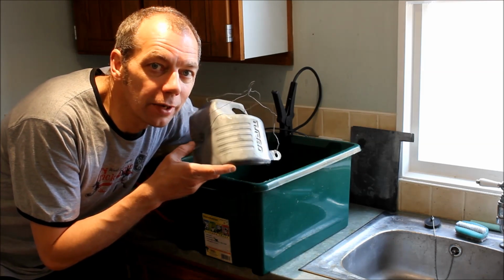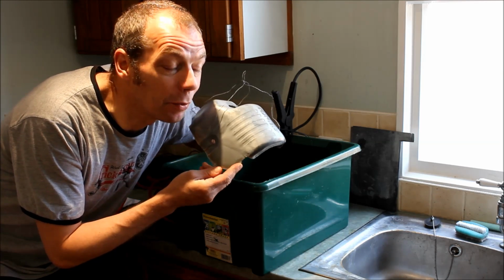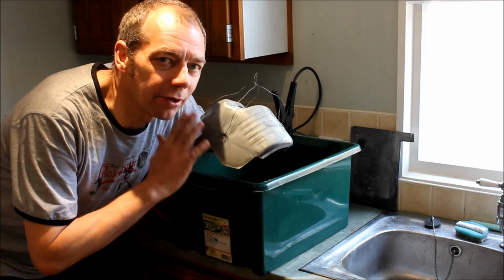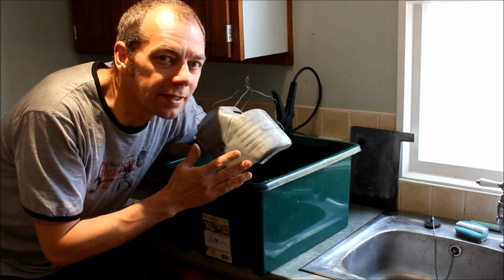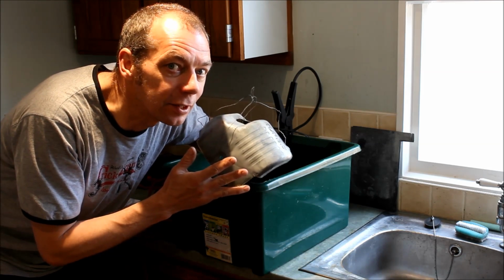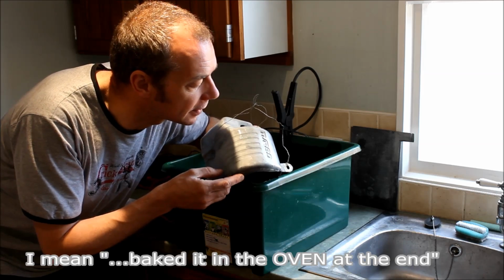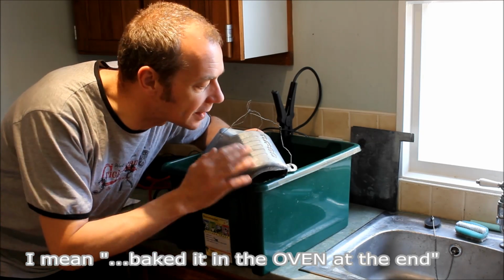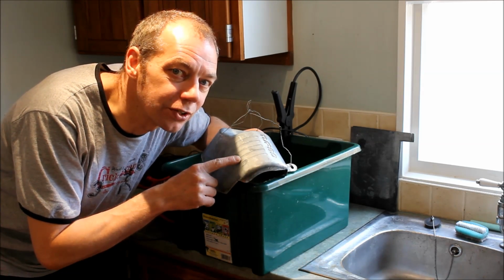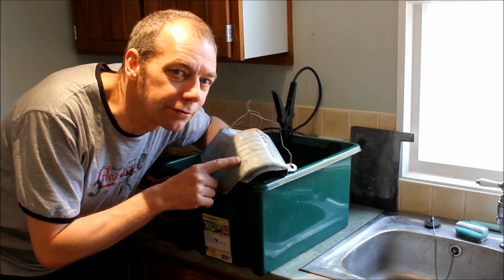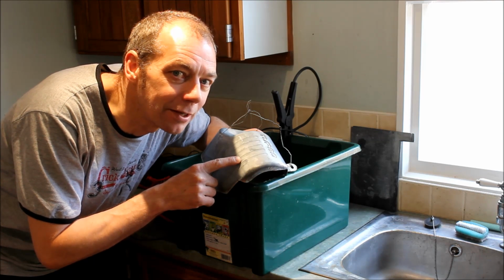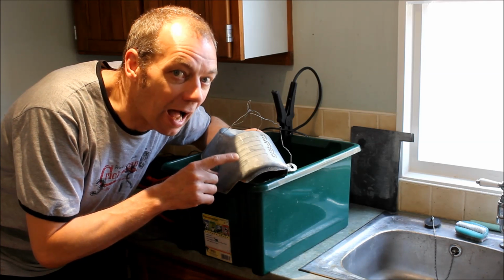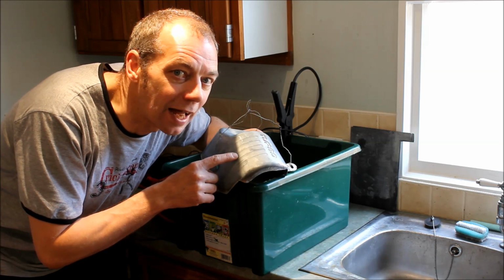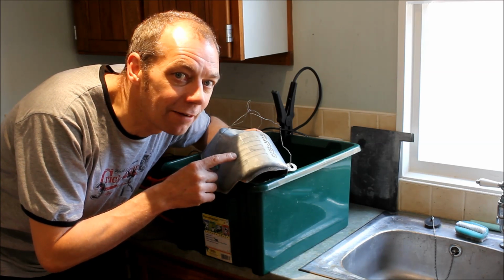Well, there you go. In the end, it took 6 attempts, but we did finally manage to get it to plate. We've got a nice, reasonably even coating of plating all over, which more importantly hasn't come off when we've baked it in the oven at the end. I had to drop the current right down. In the end, I plated that at just 2 amps for 4 hours for a total plate thickness of around 12.5 microns. And that's the highest current that part would stand without burning or blistering afterwards.